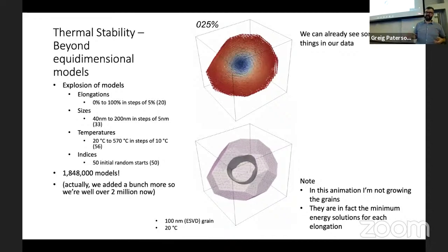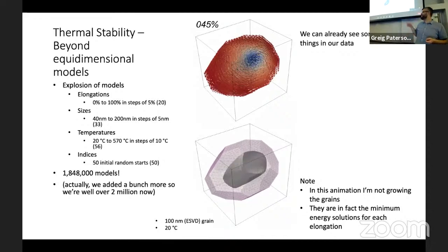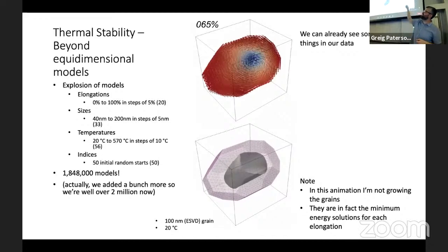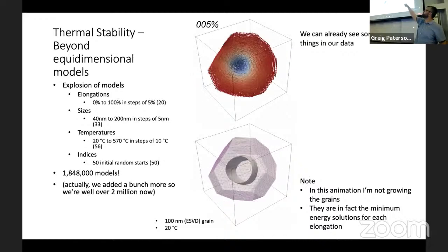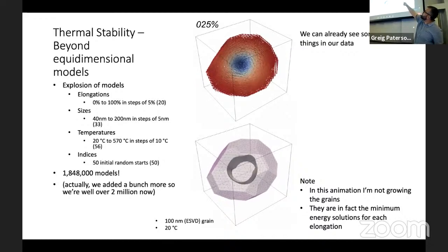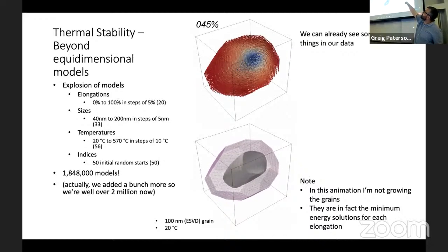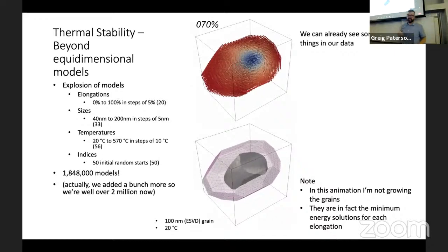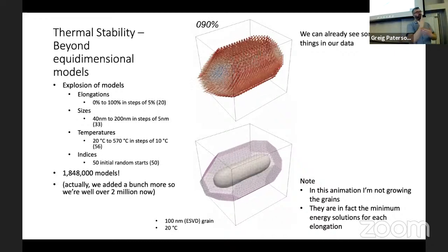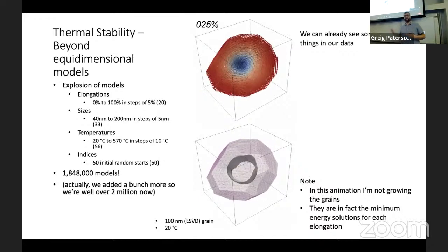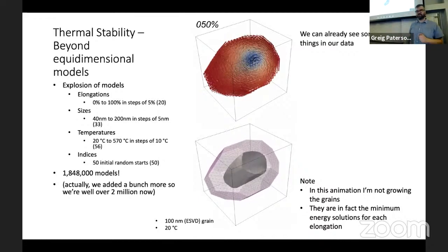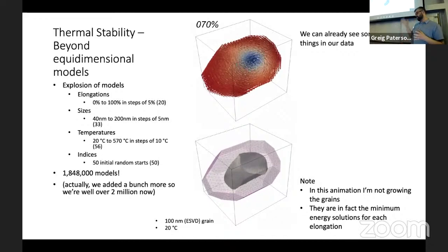In single domain theory, we would expect the net remanence, or the net magnetization, to point along the axis of elongation. This is not what's happening in these grains. Watch as it increases there. The net remanence is perpendicular to the axis of elongation, and so that's its most energetically favorable state. And that has big consequences on